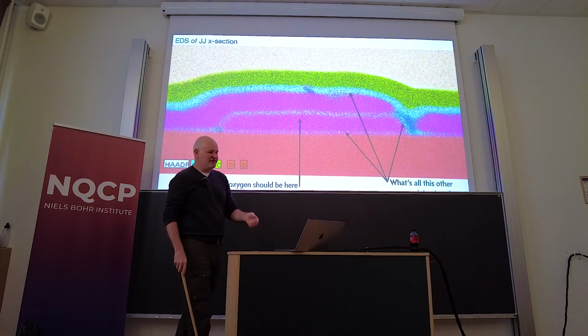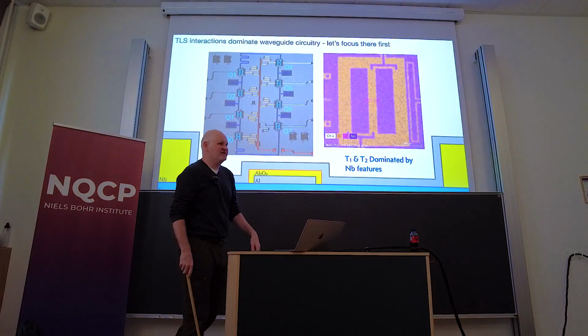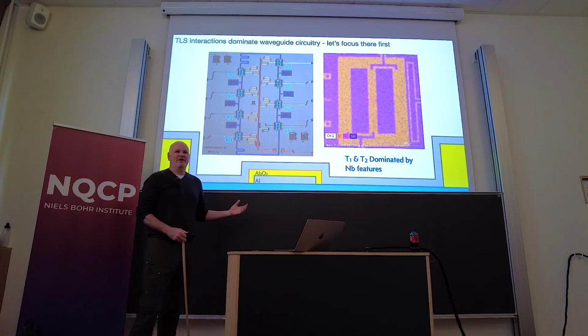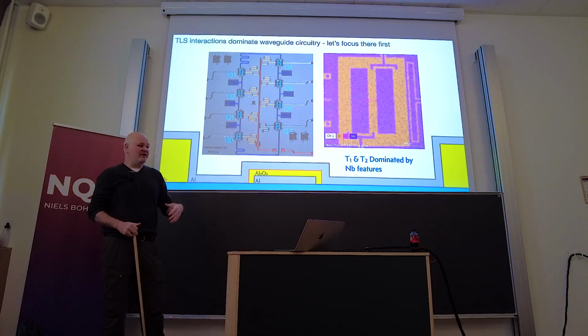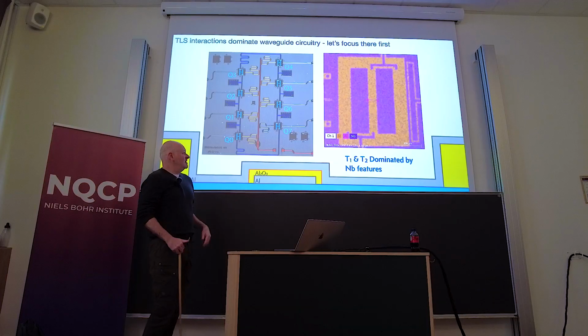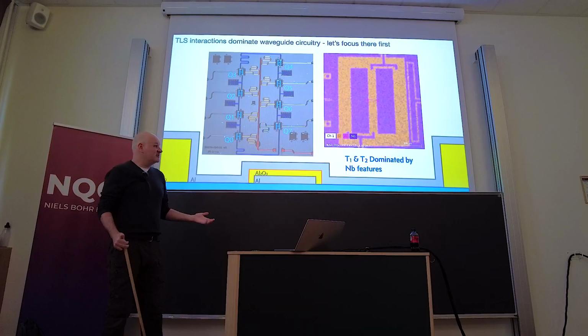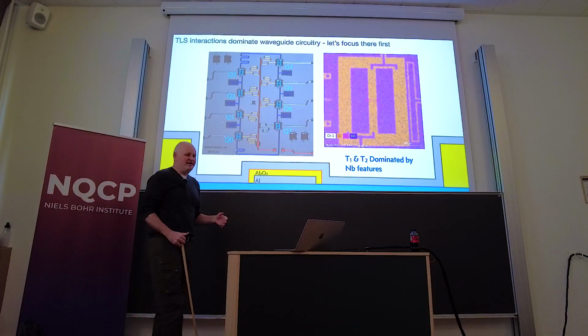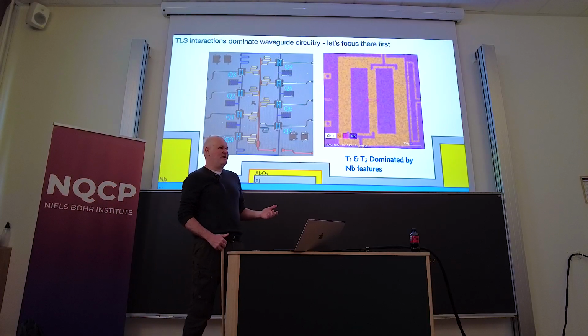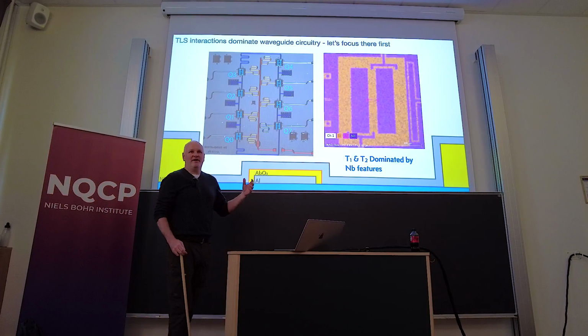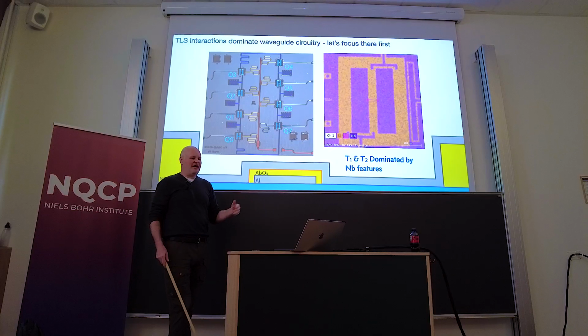However, the Josephson junctions are not really the biggest source of loss in the devices that we were looking at. The biggest source of loss in the coherence was actually from the resonators. So these are RF circuitry. And there's a lot of ways to lose energy in these circuits. And it was pretty well understood at this point that most likely the lack of improvement was coming from these resonators.